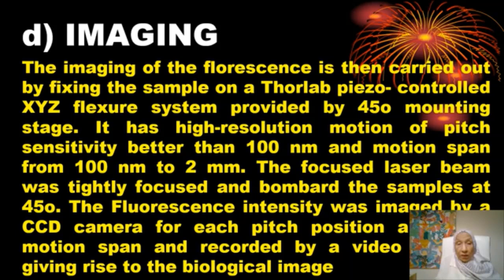So what we did actually, the imaging of the fluorescence is carried out by fixing the sample on a Thorlabs piezo-controlled XYZ flexure system provided by a 45 degrees mounting stage. It has high resolution motion of pitch sensitivity better than 100 nanometer and the motion span from 100 nanometer to 2 millimeter. The laser beam was tightly focused and bombarded the sample at 45 degrees. The fluorescence intensity was imaged by a CCD camera for each pitch position and the motion span and recorded by a video system, giving rise to the biological image.